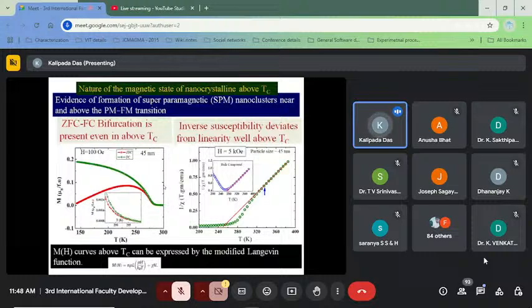And we observe the inverse susceptibility versus temperature curve, and we see that 280 is the ordering temperature, but above 280 Kelvin, nonlinear behavior of the nanoparticle is found, but it is absent for the bulk counterpart.